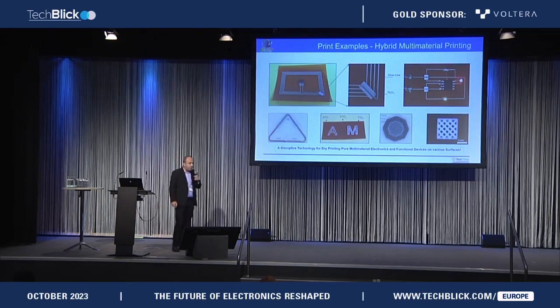So beyond silver and copper and metals, you may want multi-material printing and maybe printing multifunctional materials. Here is an example of printing silver, and then in between these cross lines, we printed aluminum oxide, and then continued the silver line on top of this, and you can create this bridge. Same thing here. You have a silver line, aluminum oxide in between. We can print side by side silver, tin oxide, zinc oxide. Same thing here, BTO, tin oxide, titanium dioxide, or we can print on top of each other and create stacked layers as you wish.